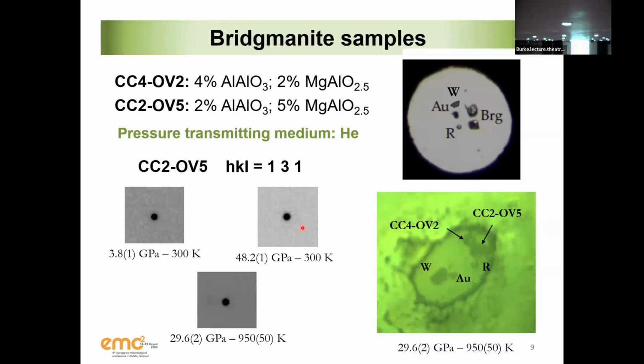When I started my career, I thought I would never have been able to go so high in pressure and in temperature with a single crystal. And as with everything in life, I was proved wrong, so it's fine with me. Then you can see, this is at 3 GPa, 4 GPa. This is at 50 GPa room temperature. This is at 30 GPa and 950 Kelvin. And we still can see beautiful data.